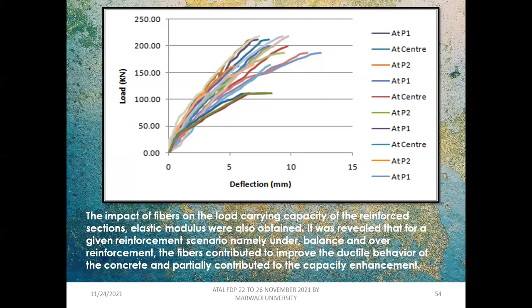This is the result chart, which discusses the loading as well as the relevant deflection that we measured consecutively at the time of loading, and which also shows the impact of fibers on the load carrying capacity of the reinforced sections. Elastic modulus values were also obtained, and it was revealed that for a given reinforcement scenario, namely under-balanced and over-reinforced, the fibers contributed to improved ductile behavior to an extent. I would say it doesn't convert it into an elastic beam, which is not possible, but up to an extent within the scenario of 5%, 10%, and 15%, the load carrying capacity was definitely improved, right?